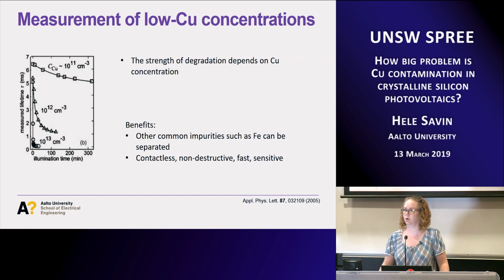So compared to all these analytical or chemical methods, SIMS and those, they can never reach these kinds of concentrations. And the problem with SIMS, for instance, is that because copper is diffusing at room temperature, and the sputtering is even heating the sample, it's really not reliable to use those methods for copper detection. So I think this is something that is quite useful for those who think that they have a copper problem.